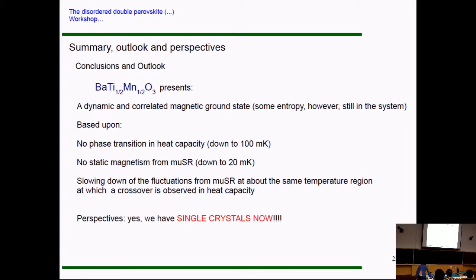And we conclude that based upon heat capacity. There is no phase transition down to this temperature. There is no static magnetism. But there is certainly a slowing down of the fluctuations at about the same region. There is what we call a crossover observed in heat capacity. And furthermore, we can correlate that with the population that we believe is still there in magnetic heat capacity, and we have an idea for the kind of emergent lattice that we have.